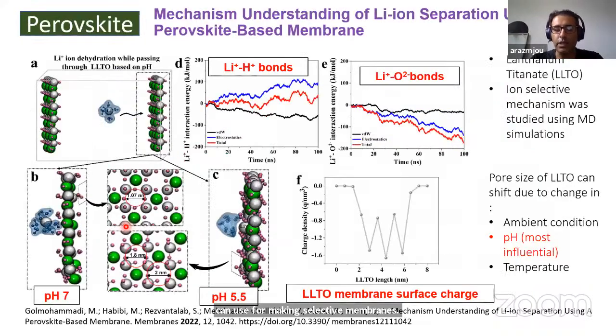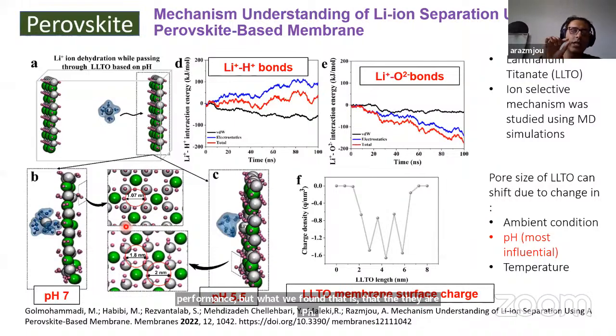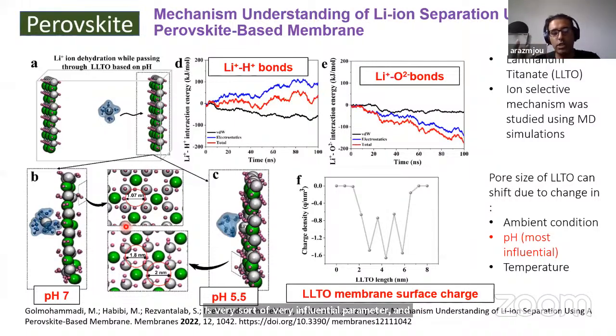Perovskites are a new family of materials that can be used for making lithium selective membranes. Although perovskite also shows very good performance, what we found is that pH is a very influential parameter, and by altering the pH a little bit, the membrane loses its selectivity. So that's very important when you're dealing with this type of material that is pH sensitive.